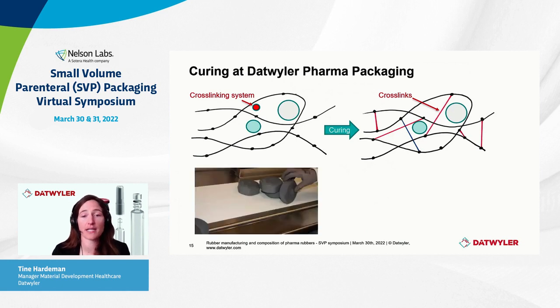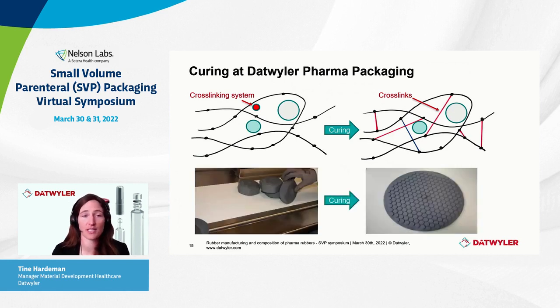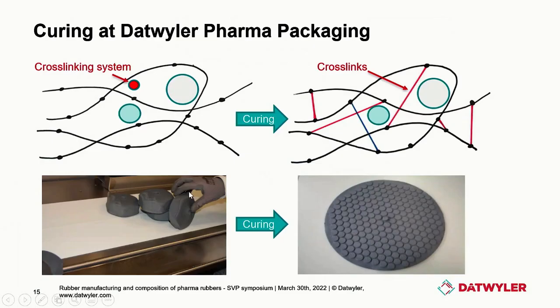Specifically at Datwyler, as you could also see during the video, this curing reaction happens during the molding. So under the influence of the high temperature, the cross-linking reaction happens. And so this is when we go from the brick of unvulcanized material towards the sheet of rubber products that you see here.